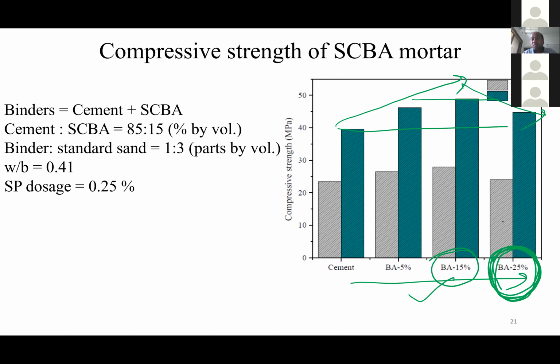Why 25% rather than 15%? Because when you look at this control concrete, this is the control concrete where no SCBA is there. Despite 25% replacement, we are able to get more than the control reference mortar. So we have to go for 25% as the best option. Okay, because in this way our sustainability is ensured more.